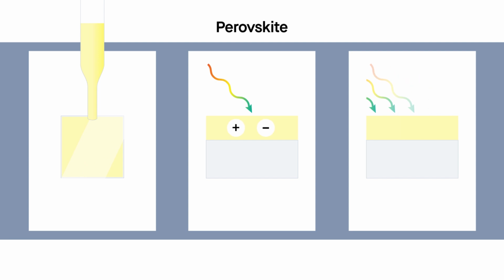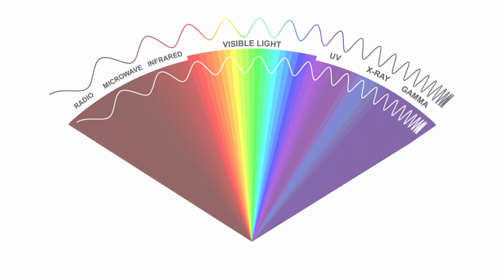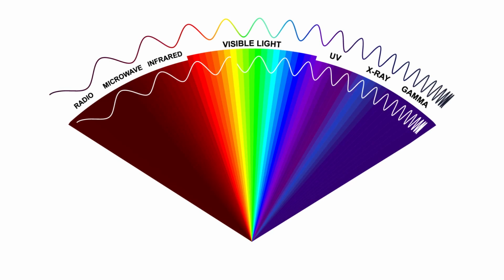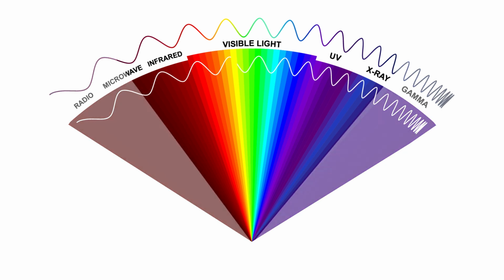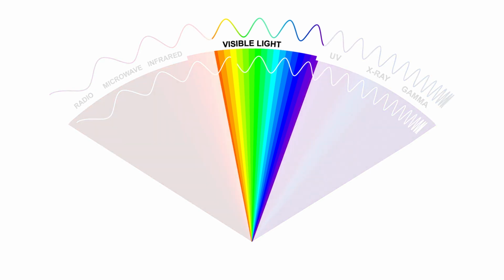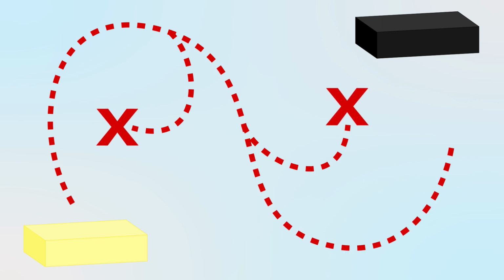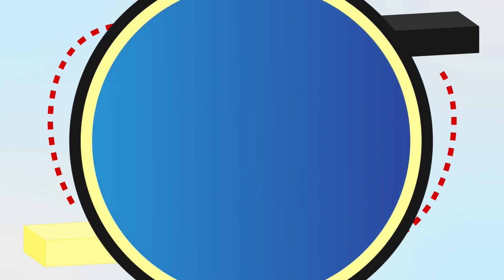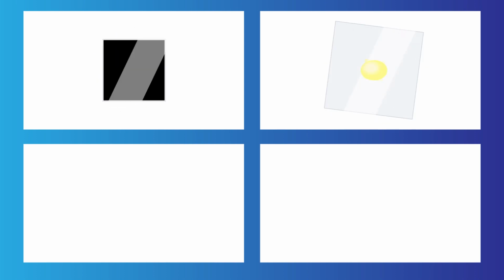You see, the problem with formamidinium lead iodide is, to put it simply, its color. The perovskite starts out yellow when it's synthesized. That makes it capable of absorbing only a narrow portion of the solar spectrum. Fortunately, the perovskite can also take on a black phase. Getting it there, however, can be a hard process to control. And even though the black phase may be successfully attained for one application, that's not guaranteed to happen for another.